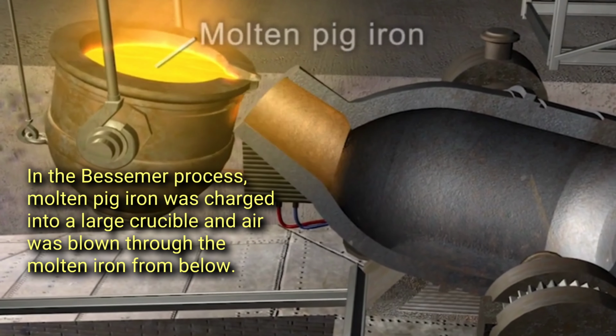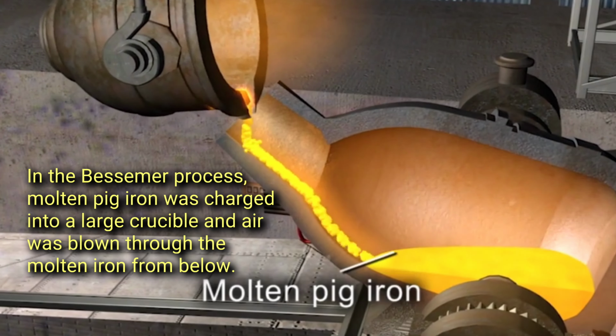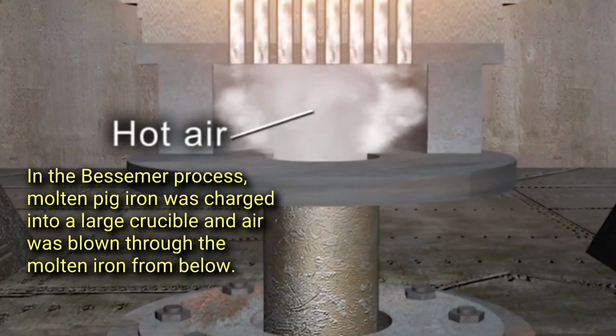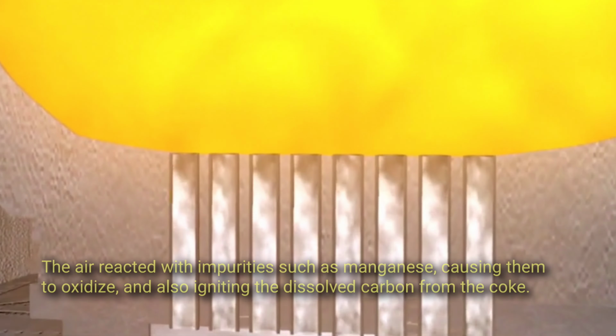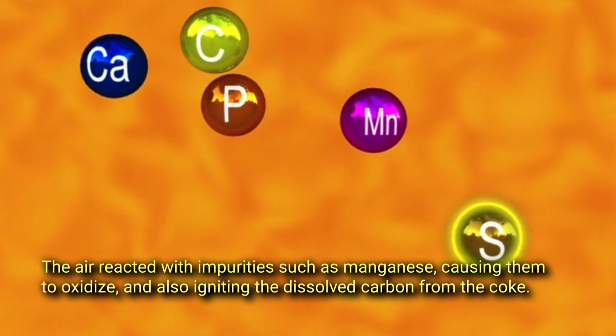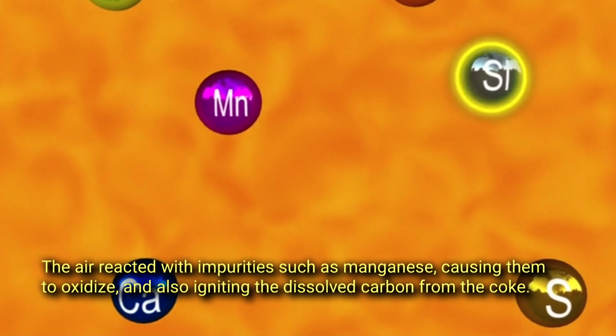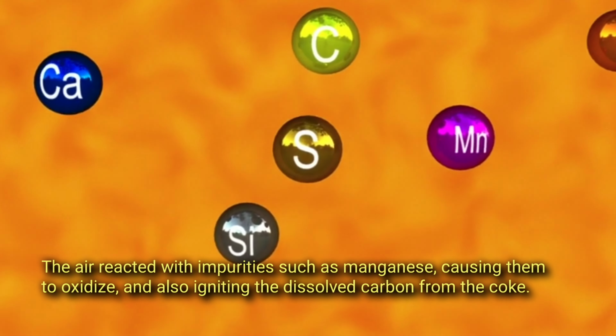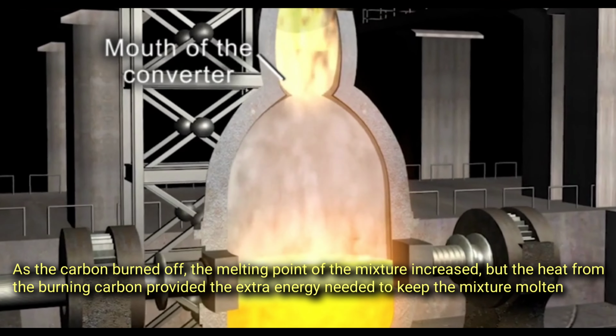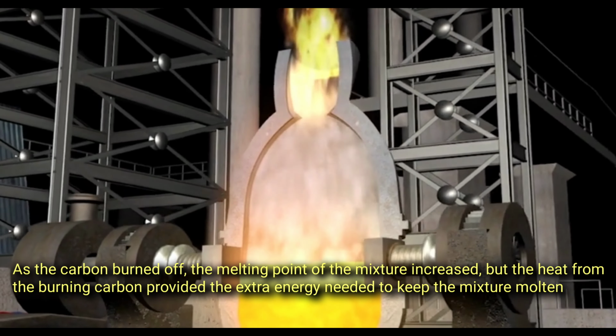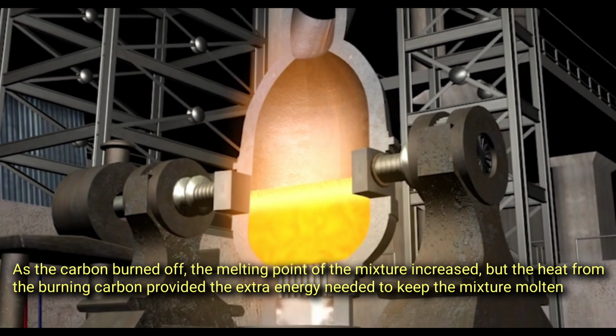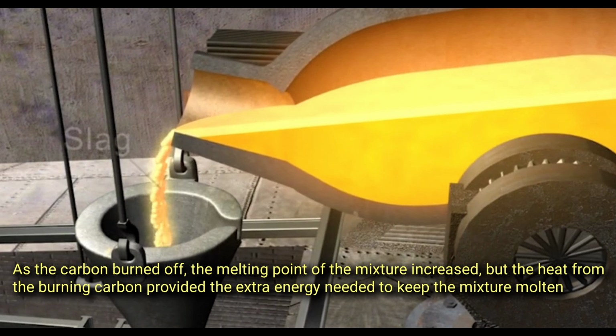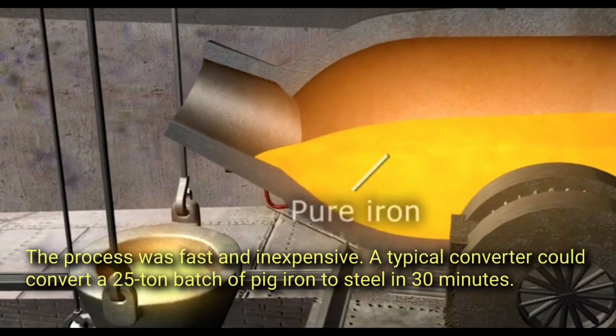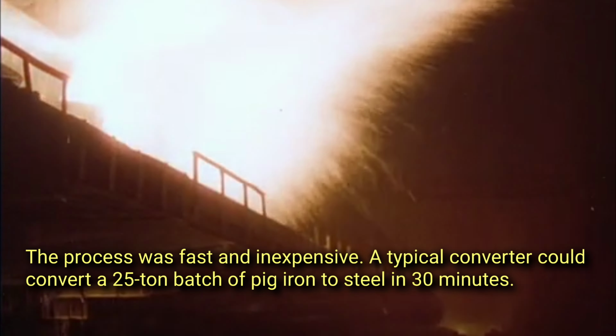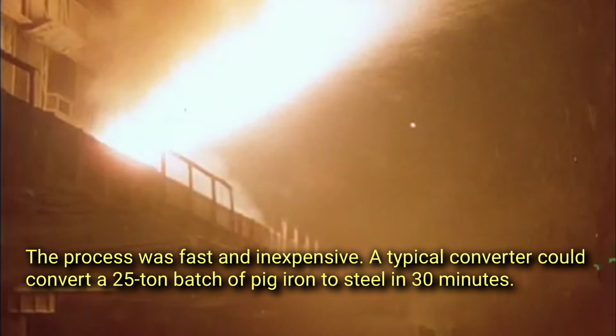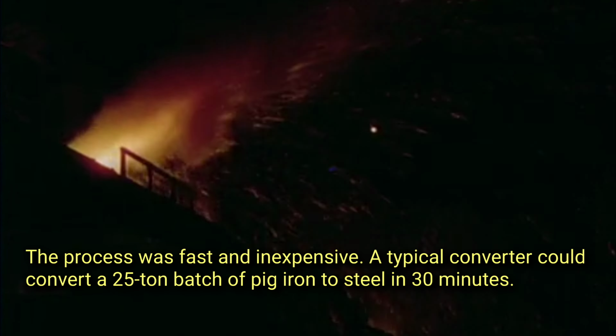In the Bessemer process, molten pig iron was charged into a large crucible and air was blown through the molten iron from below. The air reacted with impurities such as manganese, causing them to oxidize and also igniting the dissolved carbon from the coke. As the carbon burned off, the melting point of the mixture increased, but the heat from the burning carbon provided the extra energy needed to keep the mixture molten. The process was fast and inexpensive. A typical converter could convert a 25-ton batch of pig iron to steel in 30 minutes.